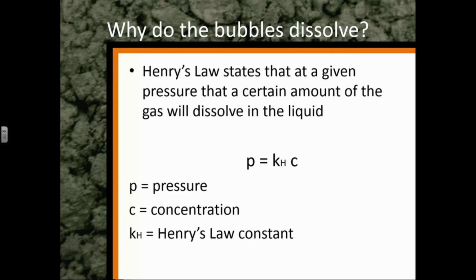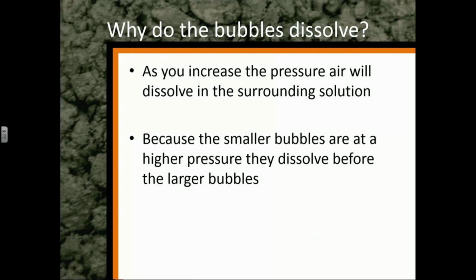Henry's law is super simple. It just says there's a constant for a certain gas and a certain liquid combination. And it says that at a given pressure, there's a certain amount of that gas that's dissolved in that liquid. So at a higher pressure, more of that gas will dissolve in the liquid. That's why smaller bubbles, at higher pressure, are going to be the first to dissolve inside the liquid. So as you increase the pressure, air will dissolve into the surrounding solution, and because the smaller bubbles are at a higher pressure, they will dissolve before the larger bubbles.